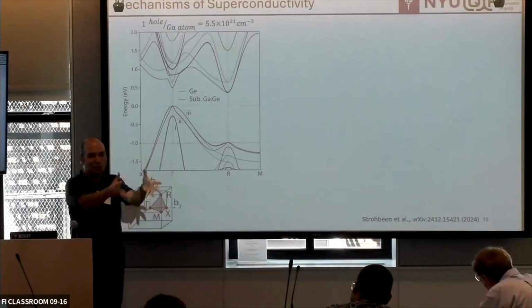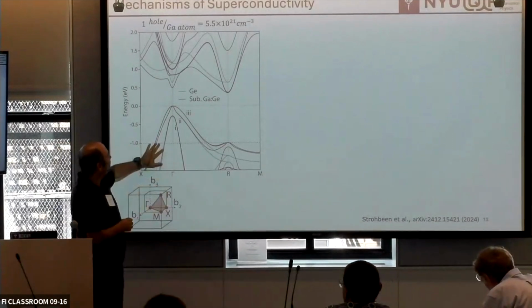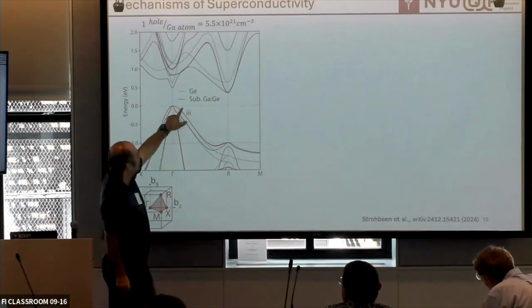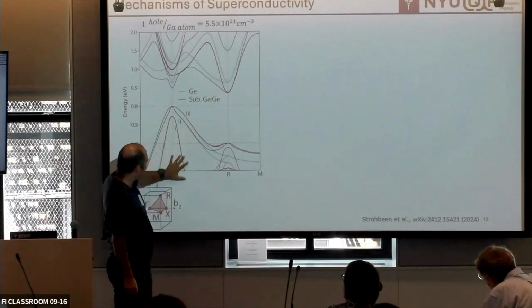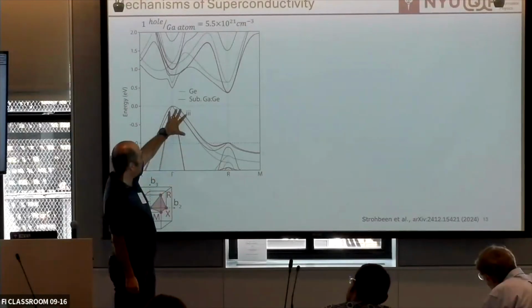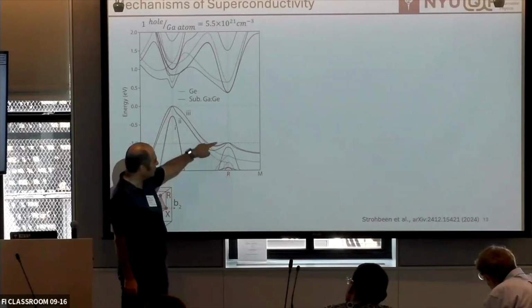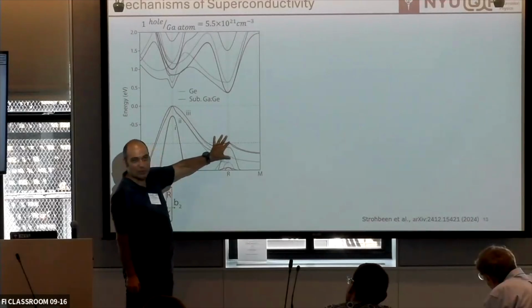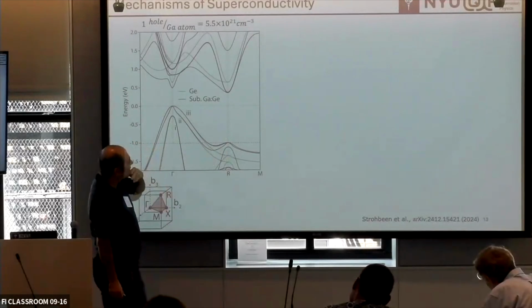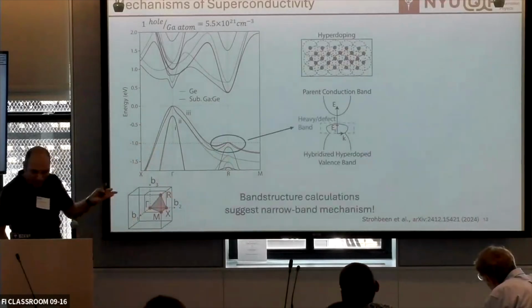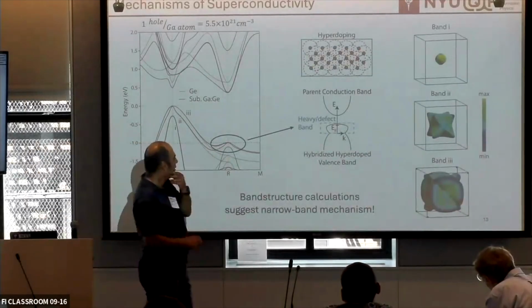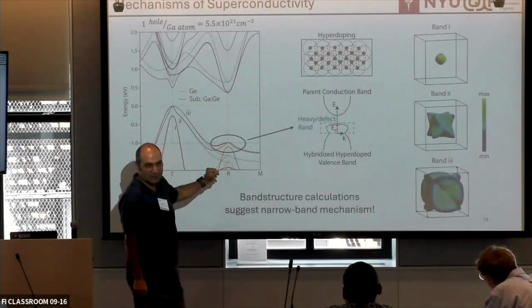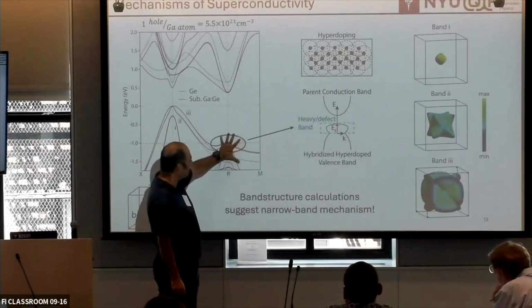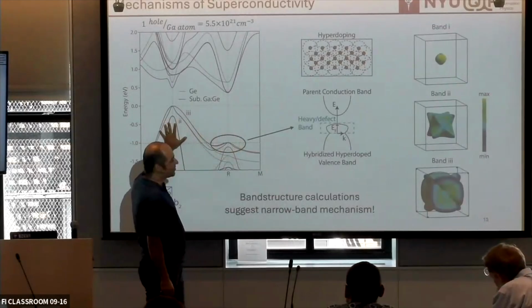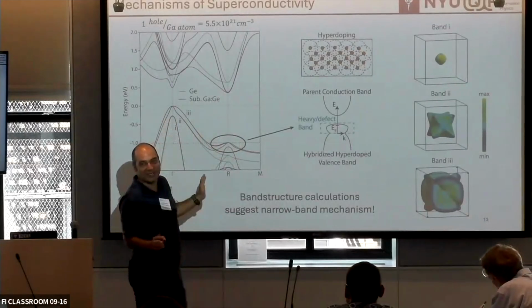there is a germanium calculation and then a doped germanium calculation, and something is different. In this diagram, the red is when it is doped, the gray is when it's not doped. On the valence band, there is not much going on at the gamma point, except at the R point, where the red and the gray change quite a bit. So we thought, and it's still a hypothesis, that at the R point maybe we are getting a flat band. This flat band creates some pocket of superconductivity that proximitizes the main band, and then the whole thing becomes a superconductor.